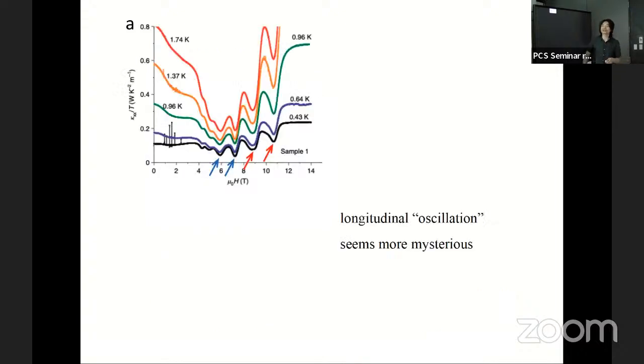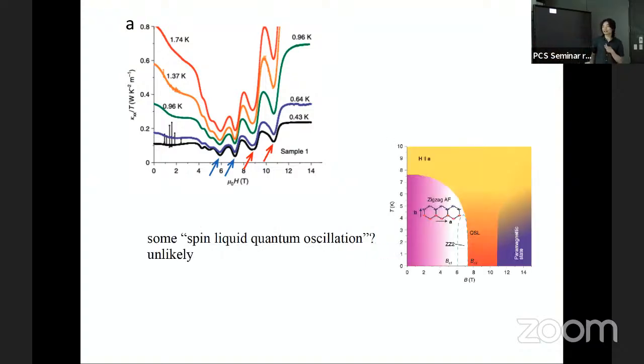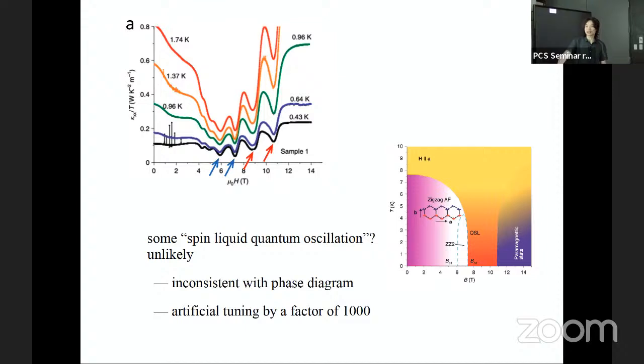So the longitudinal looks very strange. It looks like oscillation and seems more mysterious. Indeed, at the beginning, people thought maybe there's something very exotic, spin liquid quantum oscillation or anything. But it's very unlikely, for two reasons. First, it's inconsistent with the phase diagram. In the phase diagram at low temperature, this part is very well understood: the spins just have a magnetic order, and in this part the spins all point in the same direction as the magnetic field. Only in this intermediate magnetic field part is the state not very well understood, maybe a quantum spin liquid.